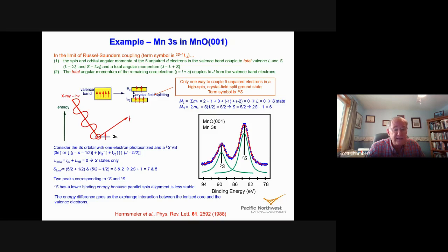There's a simple theorem of quantum mechanics that says that the energy difference in a system like this should go as the exchange interaction between the core ionized orbital and the valence orbital. That's called the Van Vleck theorem, and that number for the 3s orbital on manganese and the 3d orbital on manganese is about 5.6 eV, which is very close to what we measure. So this is an example of angular momentum coupling. Okay, are we good with that? Any questions on that before I move on?